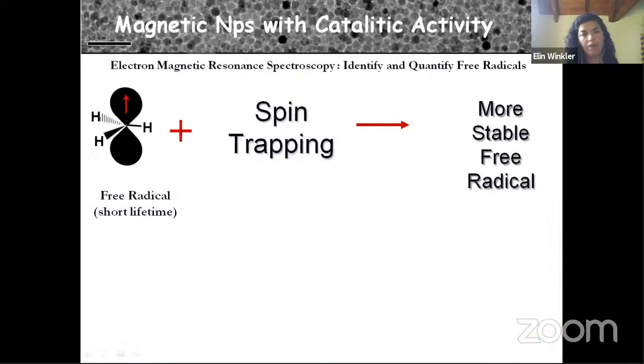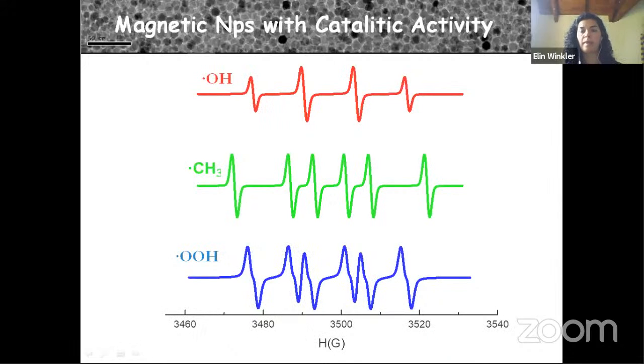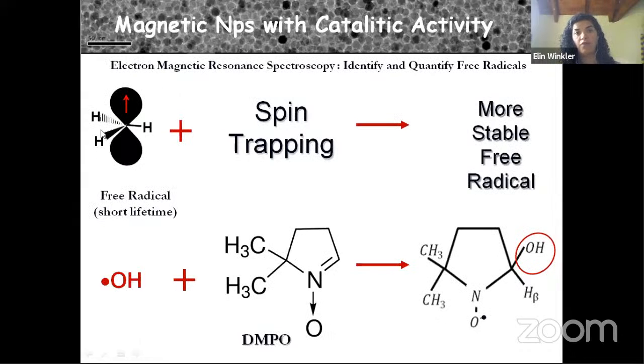So we measure, I will skip this, I'm sorry, by electron paramagnetic resonance, we can measure these free radicals. Free radicals, remember, are very reactive molecules, so this technique uses spin trapping: the radical is combined with the spin trap, and in that way we generate a small stable molecule, and we measure the resonance of this unpaired electron, which interacts with its surroundings.